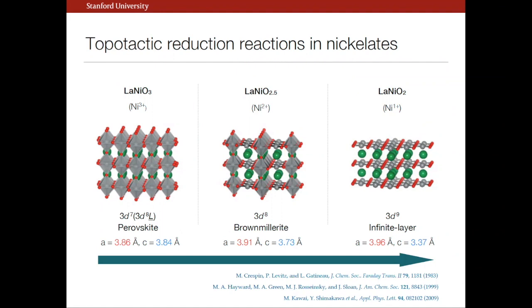The first one was to take powdered samples of lanthanum nickelate and expose it to hydrogen gas. Ultimately what is found is that there's a series of deintercalation transitions. You can sometimes stop in an intermediate so-called brownmillerite phase where we've slid this row of oxygen out. And then if you get the other one, you're left with this infinite layer structure. Now, between 1983 and 1999, there was quite a bit of controversy and debate whether this is real. It was very hard to reproduce.